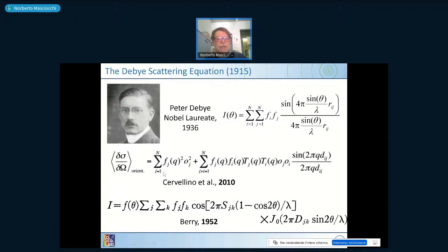self-interference term. This is a sum over the atoms of the square of this term. There is an O, which is an occupancy factor, which means that in a solid material, some sites may be vacant, and so the occupancy factor is not 1, it can be 0.95, 0.9, and so on, depending on the quantity of material which is missing in that particular site. Then you have a so-called interference term. The same term you see here, but it's just summed over a couple of i and j,